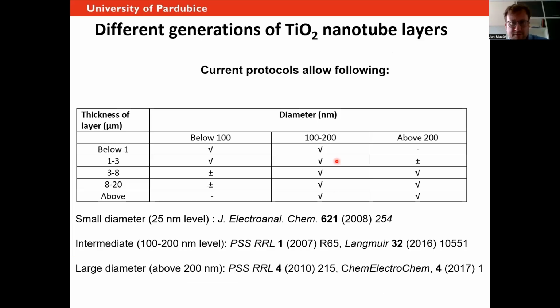All right, so now 17 years later, we are in the situation that we can relatively comfortably prepare nanotubes with different dimensions. This is similar to porous silicon or porous aluminum. So there are usually these charts, like in the anodization regime, like what voltage you need to apply to get what diameter and what thickness. And this is exactly shown here. So in the meantime, it is possible to prepare nanotubes that have diameter far below 100 nanometers, even like 15, 20 nanometers, but also far above 200 nanometers.